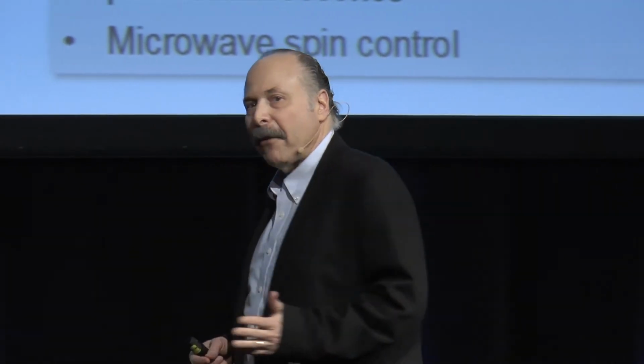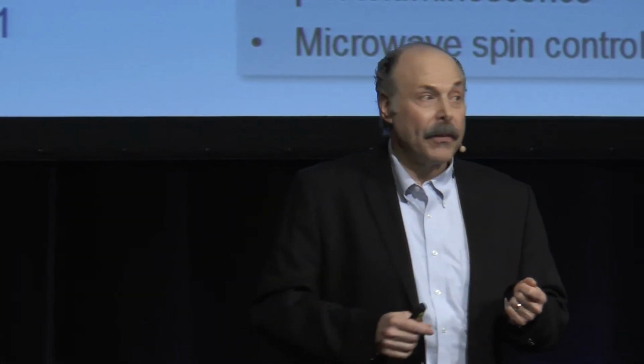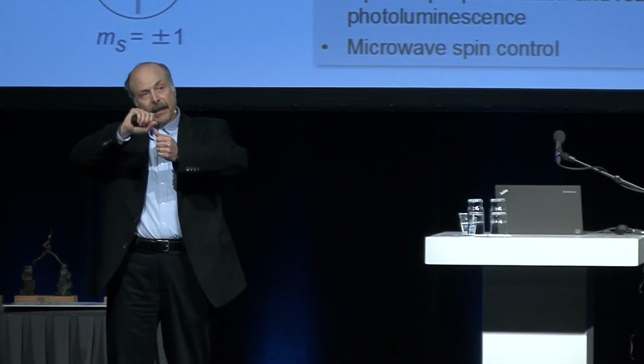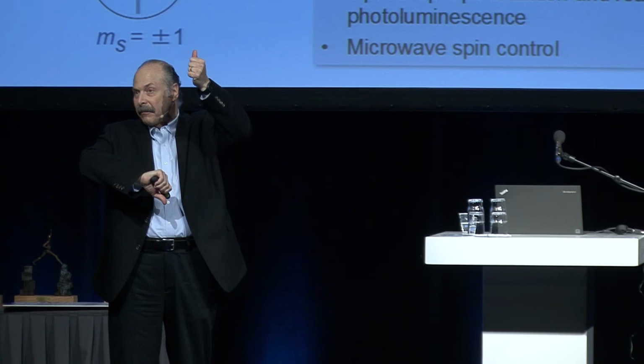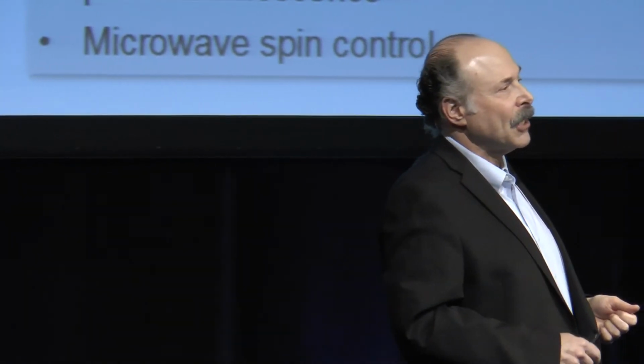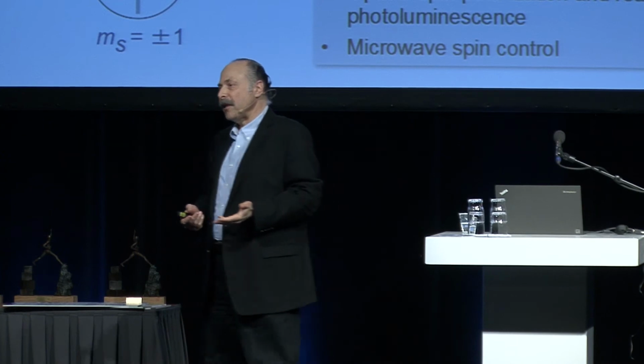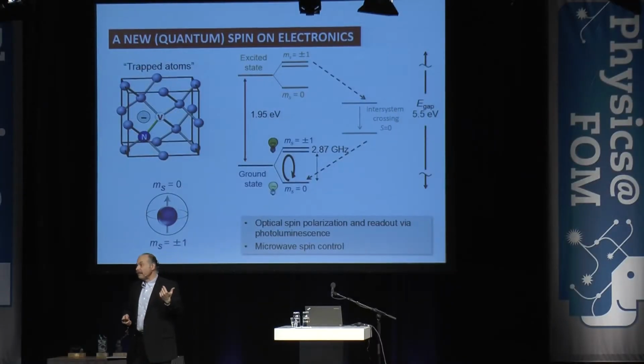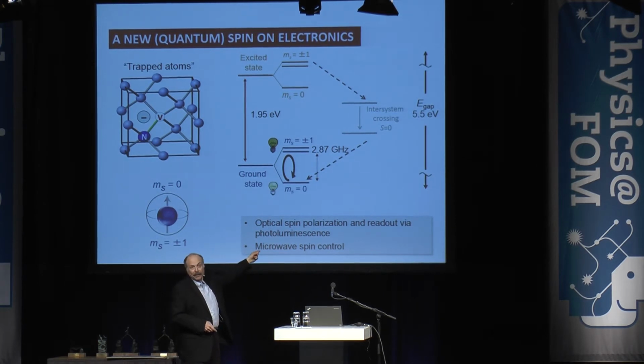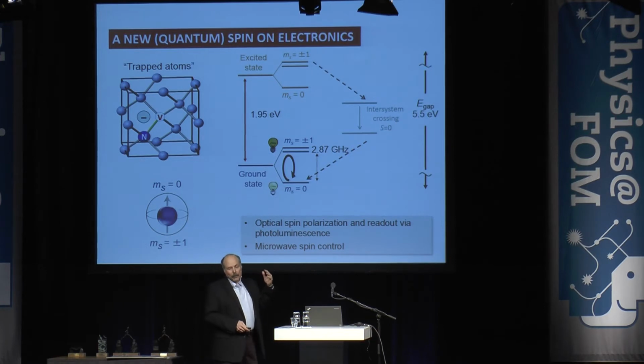Now there's a second thing. In magnetism, you typically play with spins by a magnet, right? And so the Zeeman effect tells us if you apply a magnetic field to a spin system, you lift the degeneracy of that spin system, separating spin up and spin down with a magnet. In some materials like this, there's enough internal strain in the lattice that the strain in the material lifts that degeneracy for you. So it's another remarkable thing. You can address spin states without a magnetic field. And you can manipulate the spin up and down with microwaves. In this case, 2.87 gigahertz microwave radiation, which is pretty close to cell phone frequencies. So it's very accessible, relatively straightforward to do.